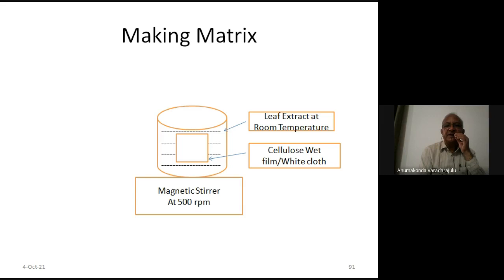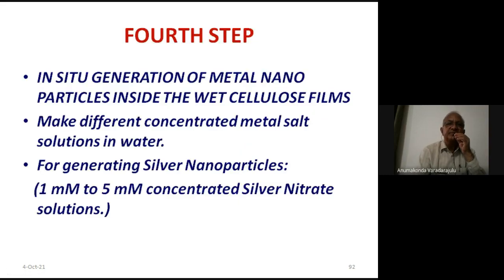So making the matrix, this is the leaf extract, and this is a wet film here, and then 500 RPM. After 24 hours, take it out. And this is the matrix, still in the wet form itself.